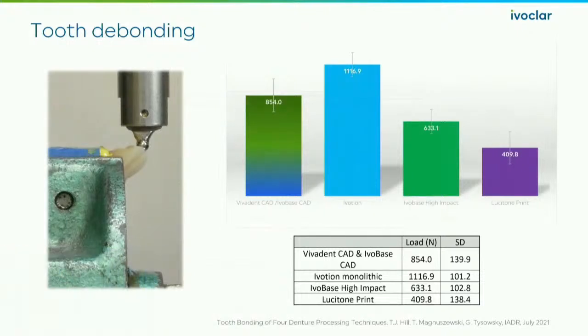So then we took the samples and decided to break the teeth and see where those failed. Now we know with the process, the Ivo base high impact process is basically our standard. We have a lot of data on that. And that's 633 newtons of force to break that tooth. And those were all cohesive failures. You have cohesive and adhesive. Cohesive is the material broke, whether the tooth or the base, or the adhesive is it just didn't stick at all. The tooth popped out clean.